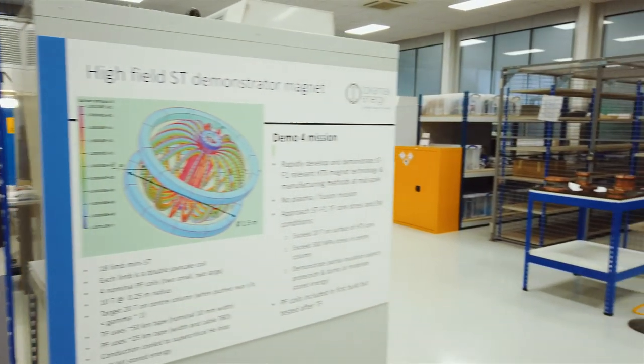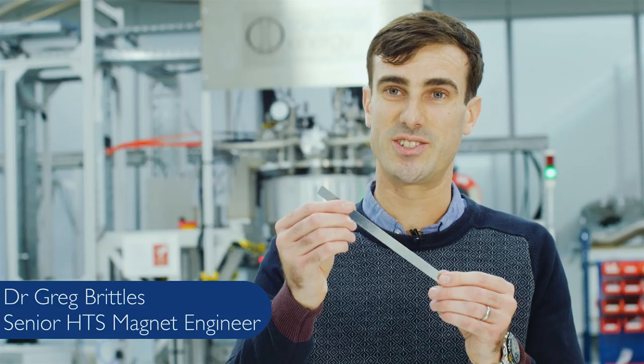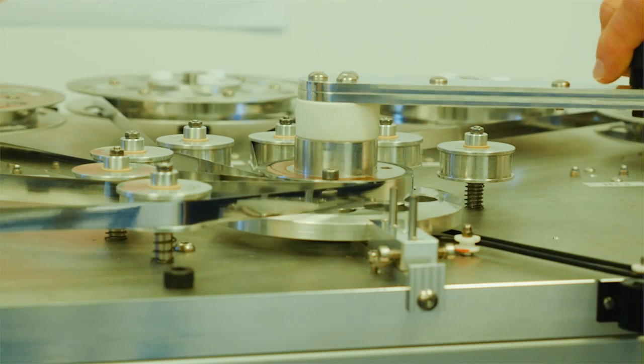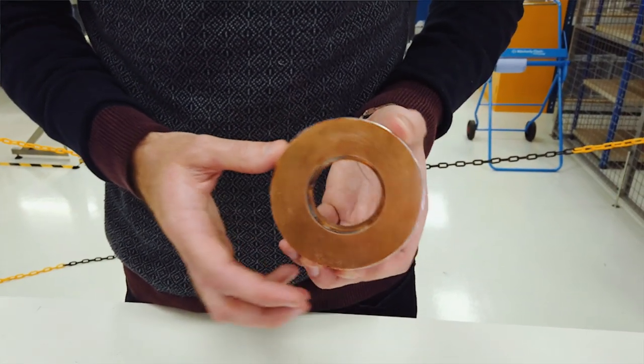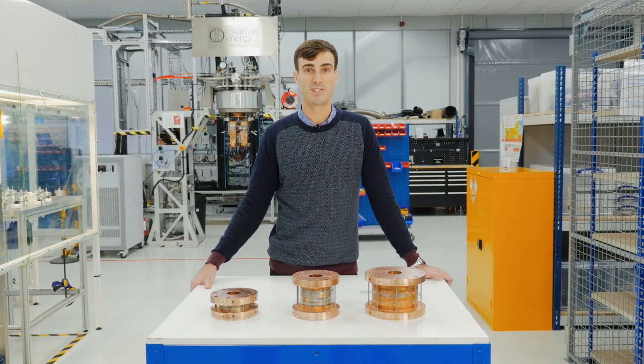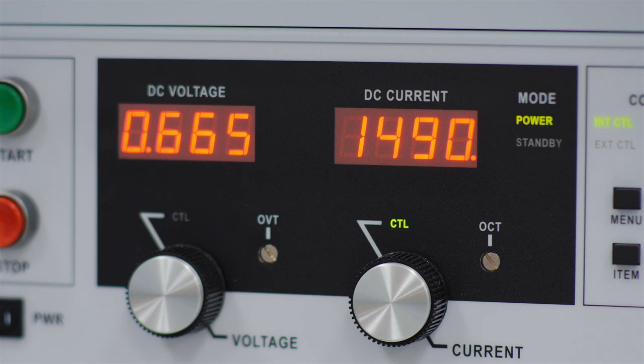This is the High Temperature Superconductor Laboratory where the team are developing HTS magnets. These magnets are an integral part of our plan to build a tokamak capable of producing commercial fusion power. Over the past 12 months we've put in a lot of work that has allowed us to turn HTS tape into a HTS magnet. We've made great steps in developing easy to assemble, scalable and robust magnet technology. We've manufactured six quality assessment coils — QA coils — in order to assess the quality from six suppliers across the world. We test these in our in-house HTS magnet test facility, and we've been blown away by the performance of these coils, in particular their stability. We've found that they're able to be operated at thousands of amps beyond their usual current capacity, because high temperature superconducting wires are stable operating in this dynamic environment.